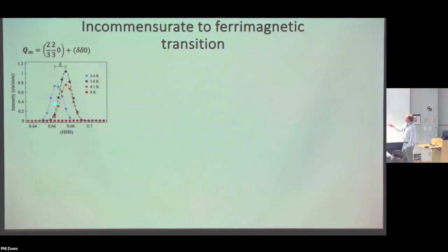So what's shown here actually tells a lot of the story. At 8 Kelvin, which is above the phase transition, there's no peak in this range of wave vector. This is along the HH0 direction, so it's an in-plane, in the triangle plane wave vector. But then when we cool down to 4.1 Kelvin, there is a little peak that develops. That peak is not at a rational fraction of the wave vector, which means that it looks like an incommensurate structure, or maybe a very, very high order rational fraction, possibly.